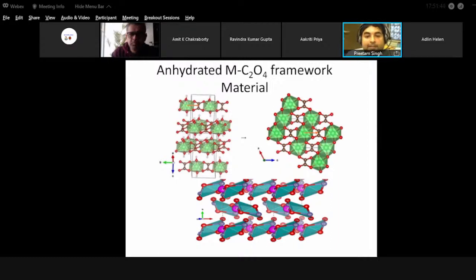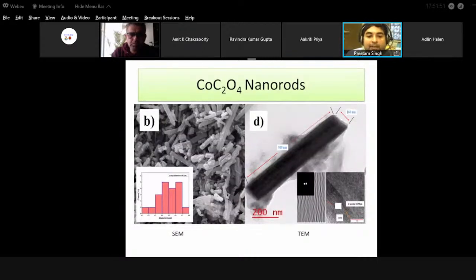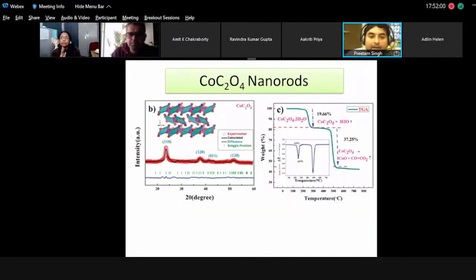The ions, especially in terms of aqueous electrolytes, can penetrate them along, and we can get much better density and performance. So we have recently done work on the CoC2O4 nanorods, or the cobalt oxalate nanorods. And see what we have done. If you take cobalt oxalate, generally you precipitate it in the form of a hydrated material. So this is the way they form the framework.